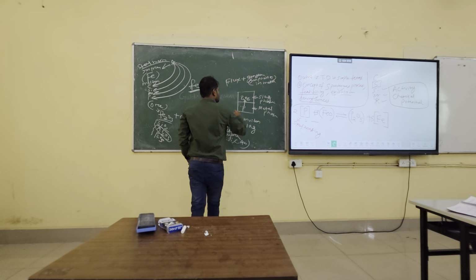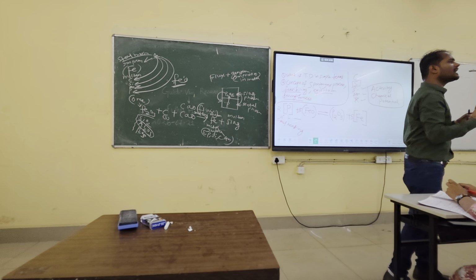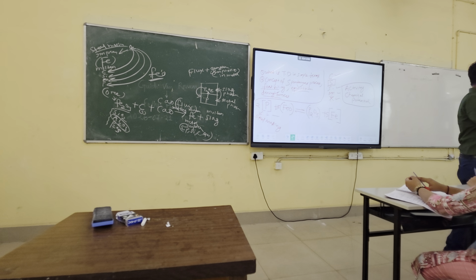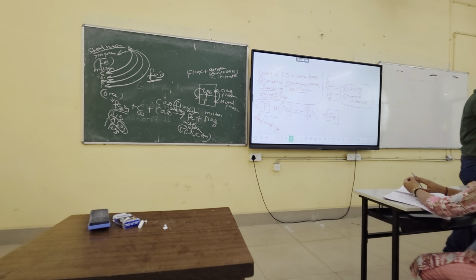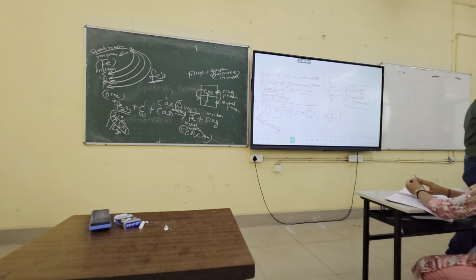So what can be done? Earlier the activity of phosphorus was higher here. Later the phosphorus activity has increased here, so the phosphorus may again come back. It is going like this, again it may come back. So you want to stop it. So what can be done? If you want to stop the phosphorus from coming back into the metal, you have to reduce the chemical potential of the phosphorus in the slag so that it will not come back. Or you have to reduce the activity of phosphorus in the slag so that it will not come back again. So that's why you are adding lime into the process.